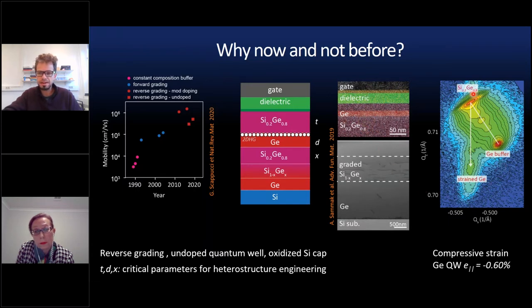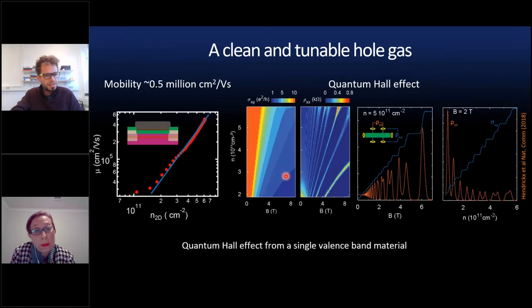And if you do X-ray characterization, you can measure the strain levels, and they're basically as you want them. And here what you have to keep in mind are these three critical parameters, which are the quantum well thickness, the separation from the oxide interface, and the composition of the germanium concentration in the alloy. So by playing with these three knobs, we can really tune a lot about this structure. And we've done so, and we achieved a really high quality material for hosting qubits. It has a mobility of around 500,000.